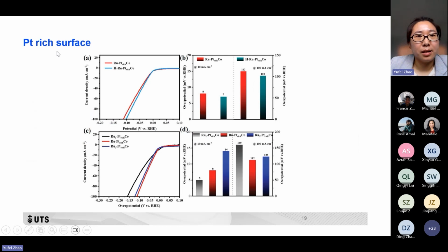And here we try to use a method to confirm that the surface is platinum-rich. We used acid to treat these materials. If the surface were platinum-cobalt alloy, we could use acid to remove the cobalt on the surface. But when we used acid to treat these materials, we found the performance almost did not change and even became a little bit better. So that means most of the cobalt is inside these nanowires, and the surface is platinum-enriched.